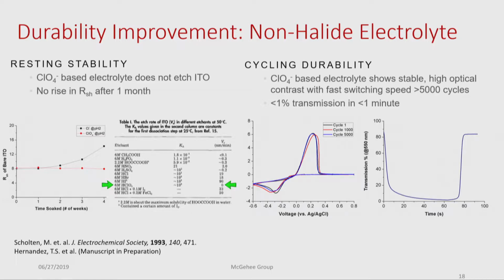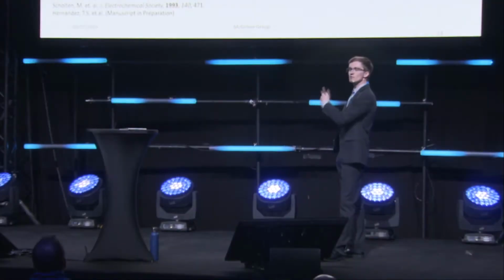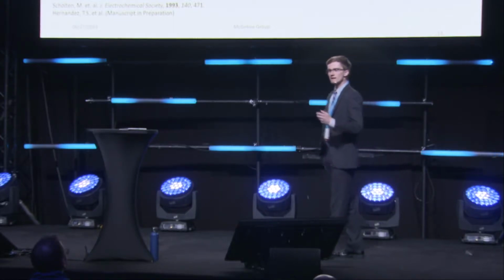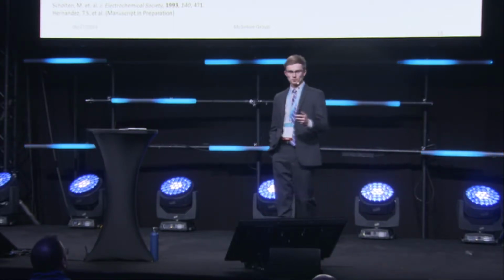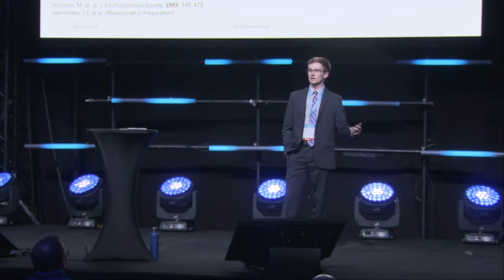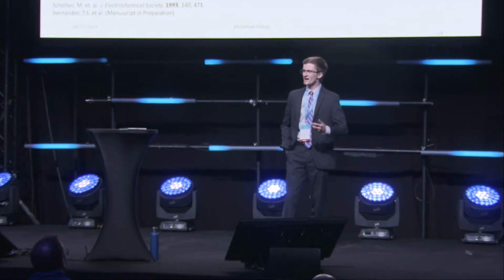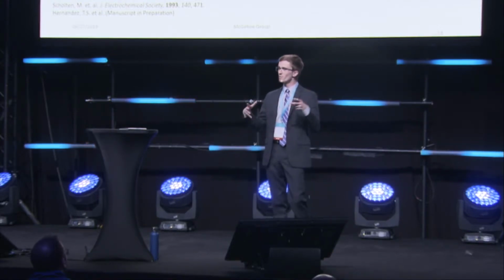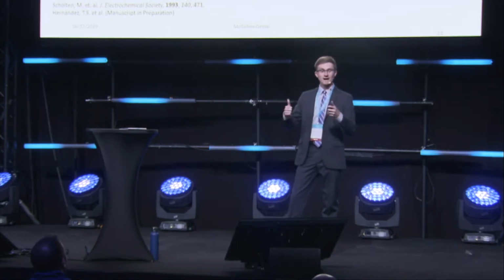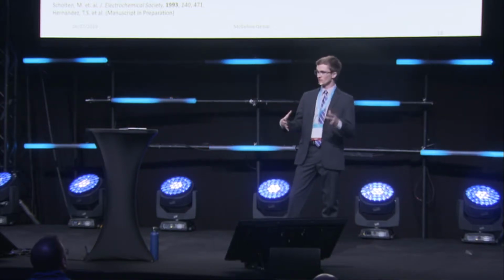One added benefit with this new electrolyte is that in addition to being stable over thousands of cycles, we're not as limited with the metal solubility as we were in our previous halide-based electrolyte. What I mean by that is we're able to dump a ton more metals into our electrolyte to drastically increase the concentration of our system.